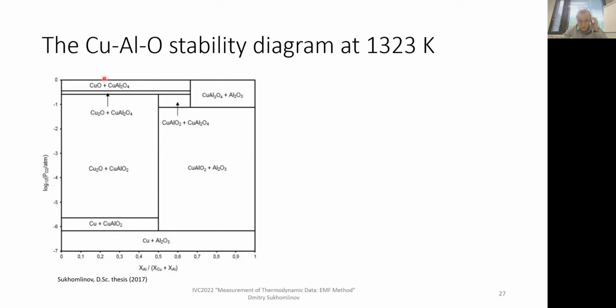And then at high oxygen pressure, like in air or pure oxygen, stable phases are CuO and spinel. And here on the aluminum rich side, it's alumina and spinel. So this is one way of illustrating, presenting data. One type of stability diagrams.